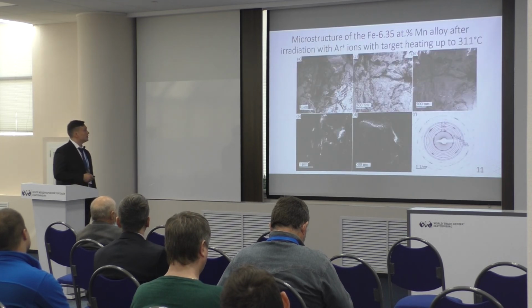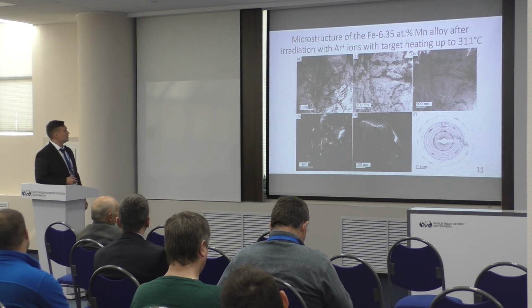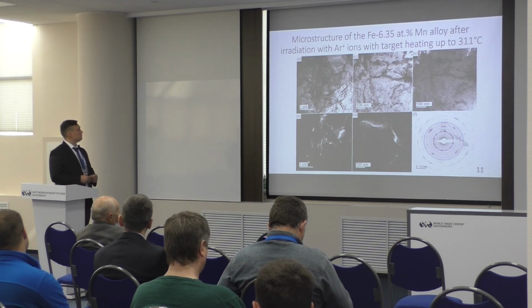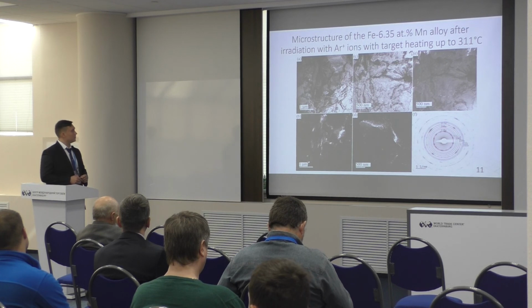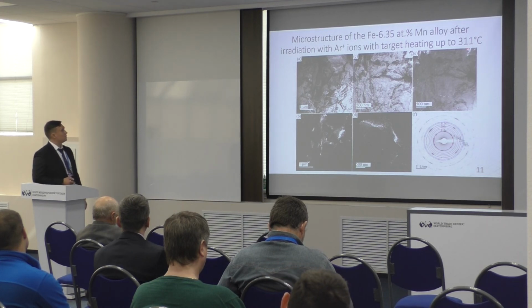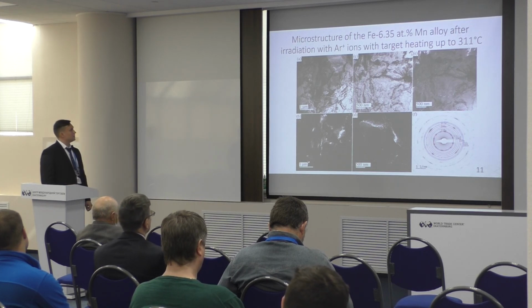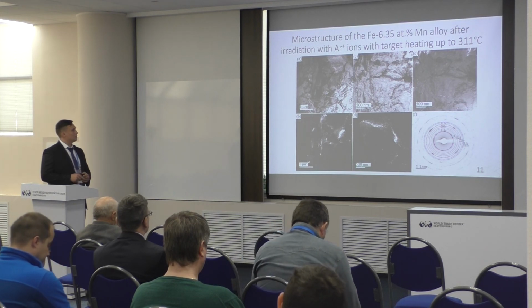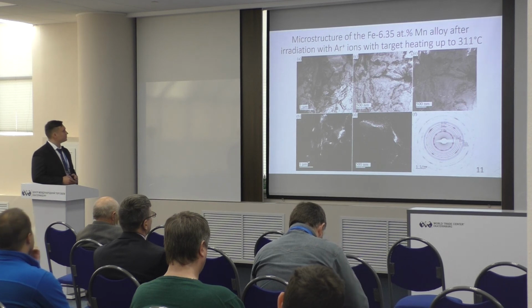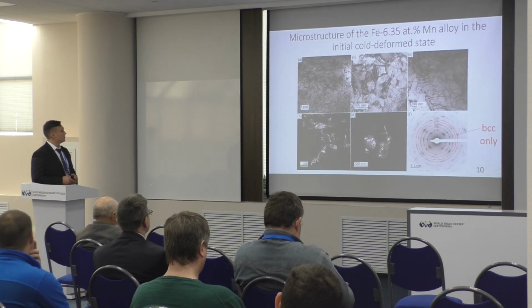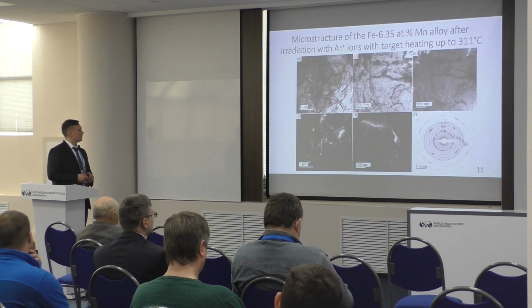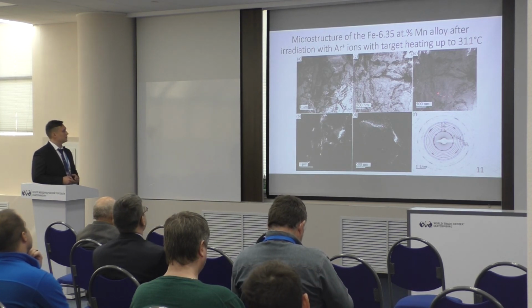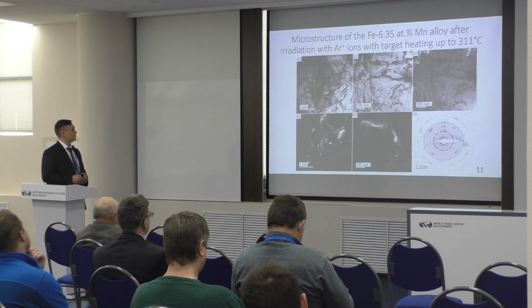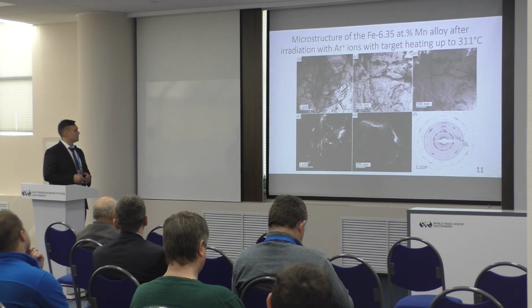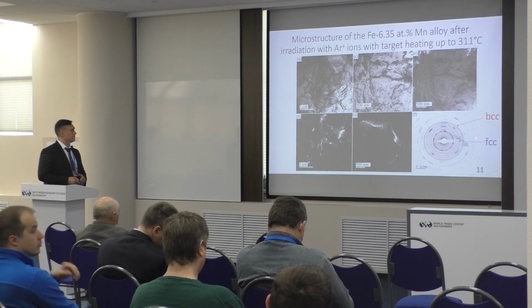And look at the next slide. These are the transmission electron microscopy patterns for the specimen after ion irradiation up to 311 degrees Celsius for only 4 seconds, and you can see the same structure, and also you can see these fragments of the FCC lattice of the gamma phase, and there were BCC and FCC Bragg reflections.